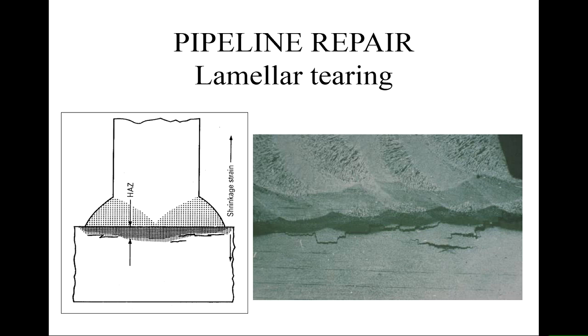And here is some micrographs showing these lamellar tears. And you can see the banding of the microstructure from this case, because this is rolled plate. So what you're trying to do is get down the number of defects, the number of inclusions in the rolled plate, so that these don't become a problem. Or if you do have inclusions, make sure they're not in lines. Try and get them distributed more uniformly in the plate.